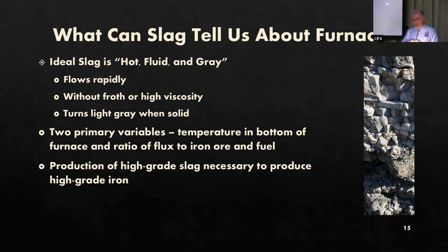The observation that the slag flows freely and rapidly means that the slag typically contains lower amounts of silica. The slag that contains too much silica would not melt properly in a furnace. So that would create other problems in the operation of the furnace. The characteristics of slag in the furnace told the furnace workers about the composition of the slag and also the temperature at which the furnaces were operated.